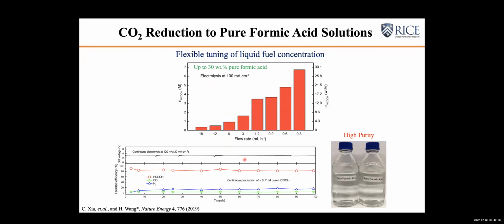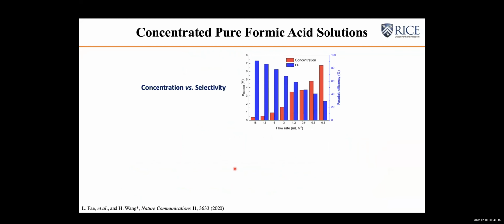Also, if you continue to produce about 0.1 moles of pure formic acid solution, that can be run stably for hundreds of hours. In this case, we demonstrated 100 hours, but now we have a new target of holding the current density at about 200 milliamps per square centimeter and running stably for 1,000 hours. We know that by accumulating more and more formic acid solution, you will sacrifice the product selectivity. This is a trade-off. Your Faradaic efficiency continues to decrease to only about 30% or so if you want to accumulate 38% formic acid solution.